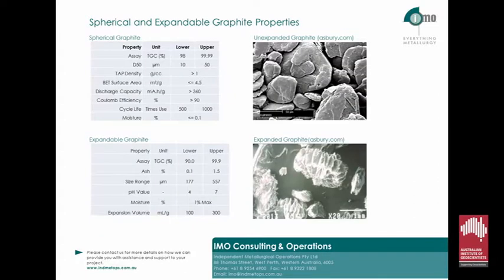You'll see the properties of both spherical and expandable graphite pasted on this slide, along with some SEM pictures of unexpanded flake graphite, which looks to be a final beneficiation concentrate, and pictures of expanded graphite. The process of producing expanded graphite is from the intercalation of appropriately sized ions, such as a sulfate ion, which can fit between the graphite layers, and then when rapidly heated, undergoes exponential expansion to produce expanded graphite. The expansion potential of graphite flake is primarily dependent on the number of graphene layers or stack height of the flake. Our research indicates that this is another growth market for, in particular, flake graphite. IMO have developed procedures which can determine graphite flake expansion potential.